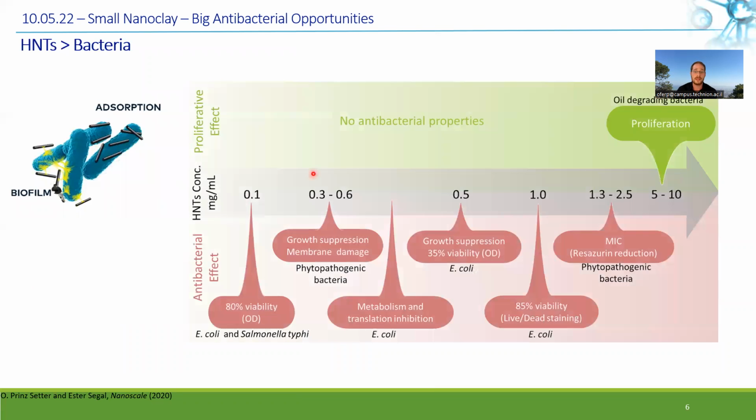And here also the answer is under debate, as we found in our review that there is all kinds of evidence in the literature, some of it even contradicting. The conclusion is very dependent on the concentration used and the method used to assess the antibacterial activity. In our experience, according to years of investigating HNTs, at least at the concentration we use, there is not a substantial antibacterial effect of HNTs, and thus some modification is needed.